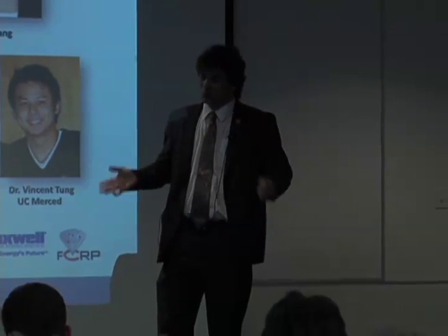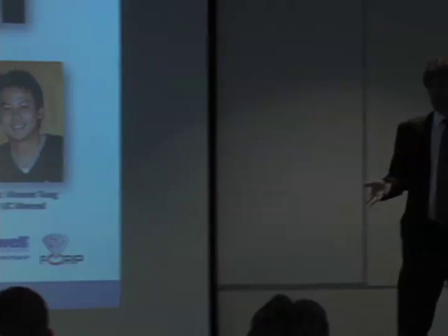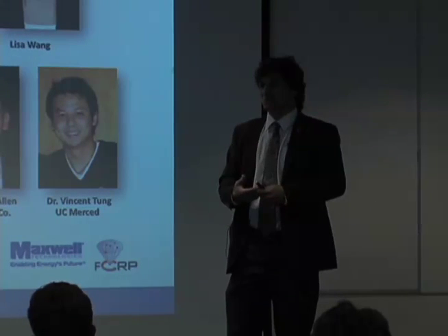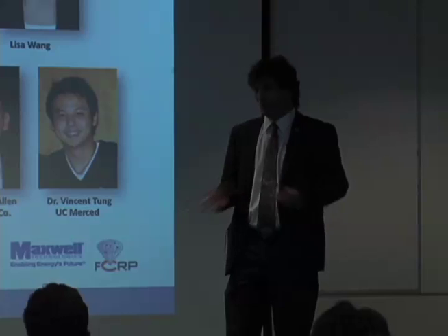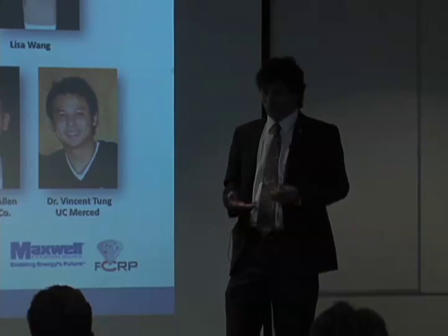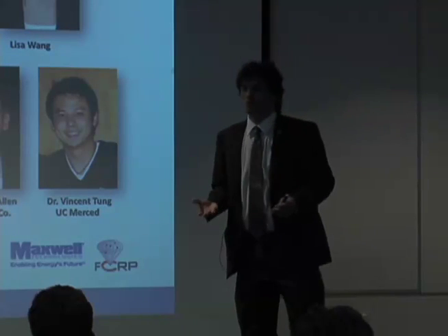We got a hold of a laser box. We've tried different colors, so the normal range is fine. I've also done a collaboration with a group at the Kennedy Space Center because they wanted to ask that question. They said we have one of the world's most powerful lasers, and of course, the first thing we told them is that if you take too much power, you're probably just going to blow it away. Well, they blew it away, but then they started attenuating their laser power, and then they said, okay, now we've got it. So I don't think it matters what wavelength you use unless you want to draw fine lines, but it is the focused laser power that makes all the difference.